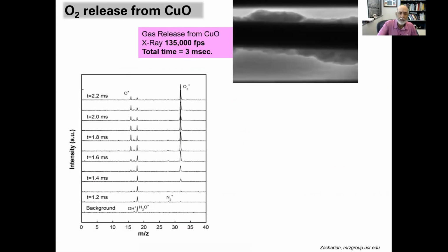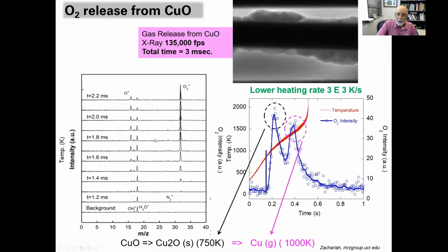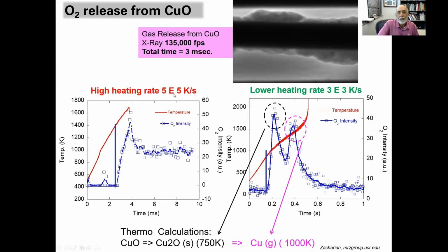And so here we can see oxygen. This is what the mass spectrometer profile looks like temporally from copper oxide as we move it in time. And interestingly, if I were to look temporally, you will see two peaks for oxygen coming out. One is CuO going to Cu2O and another is Cu2O going to copper. So we see both phase transitions, but this is a relatively low heating rate, only 3,000 Kelvin per second. If I went to 500,000 Kelvin per second, we only see one peak.